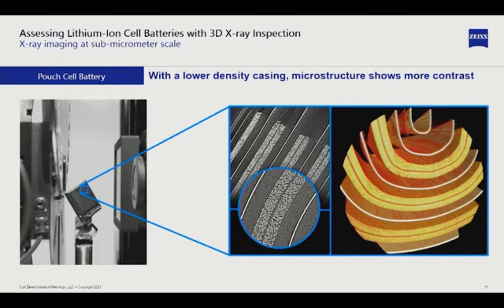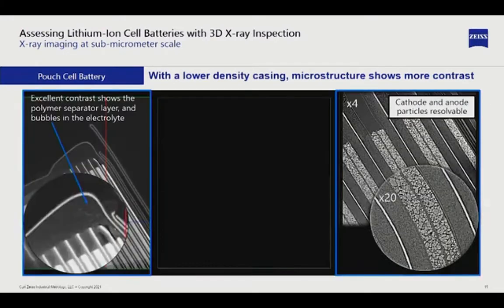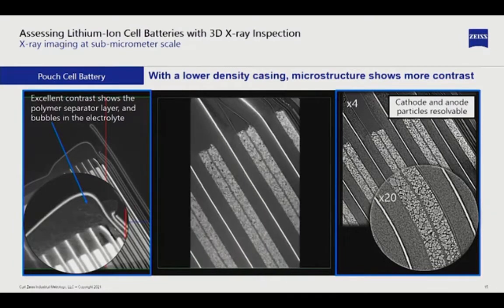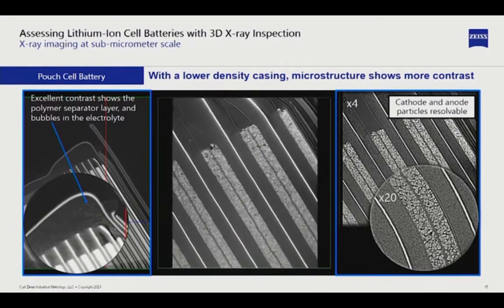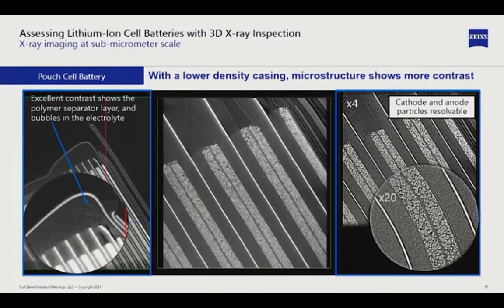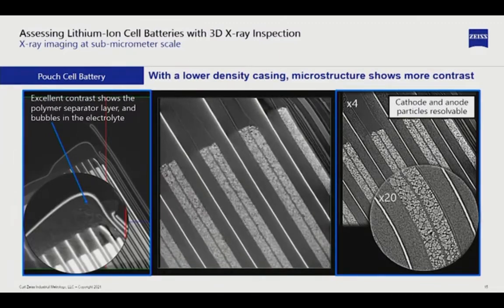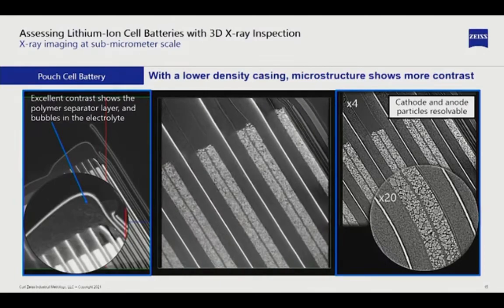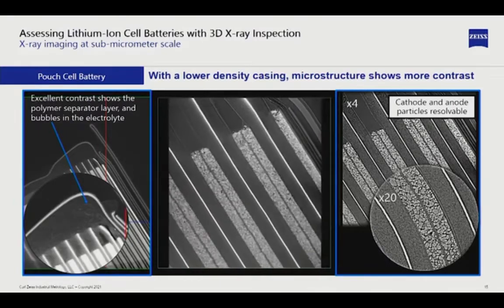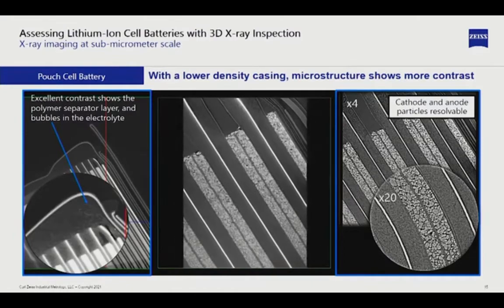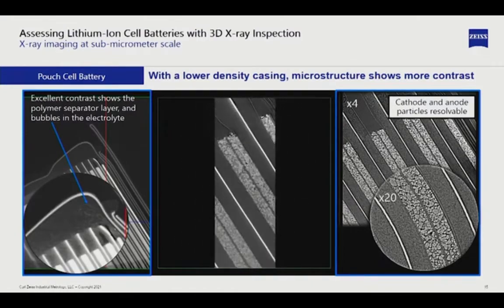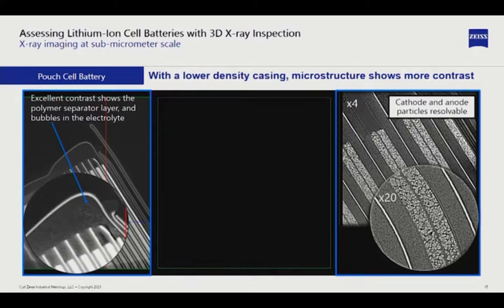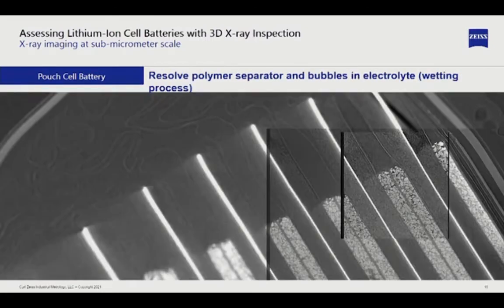So that's one of the nice abilities of the X-ray microscopes in terms of getting this type of assessment without destroying the device. And you can create all kinds of videos because you have the volumetric information and see the separation between those granular structures and see the packing. You know that if the packing is not very good, then you have low energy density packing, and that's not very good. And you also can check for other kinds of defects or delamination at the end of the battery.